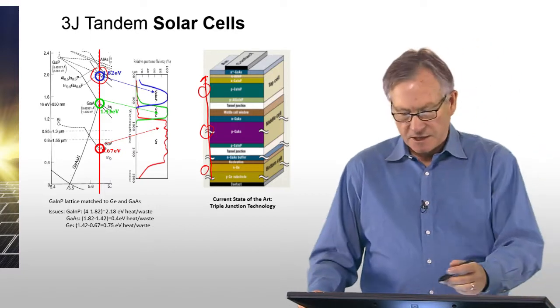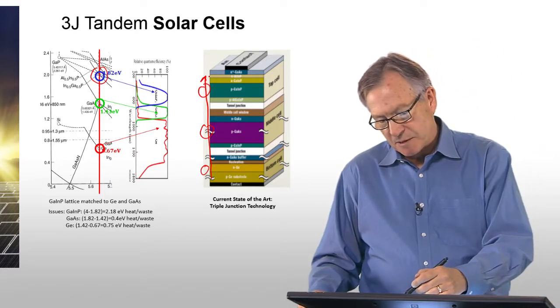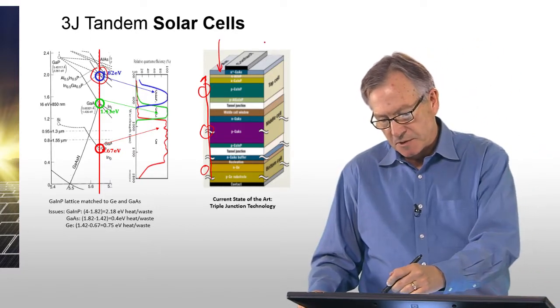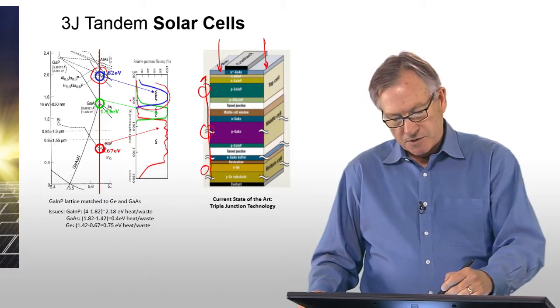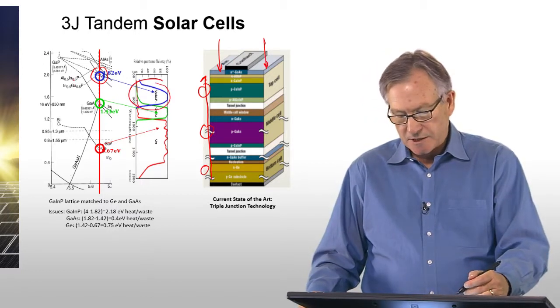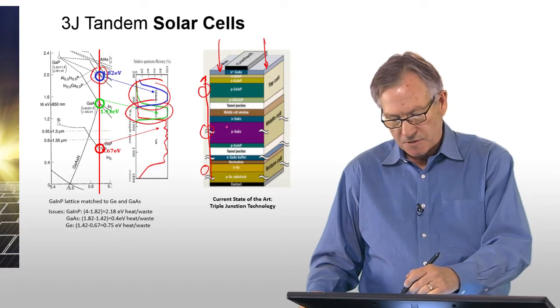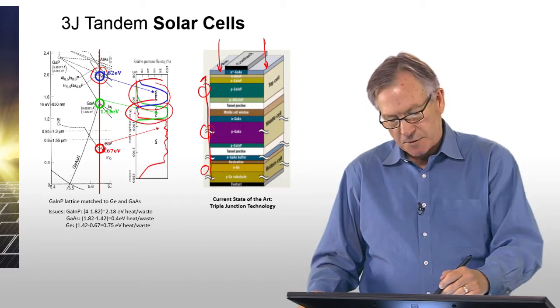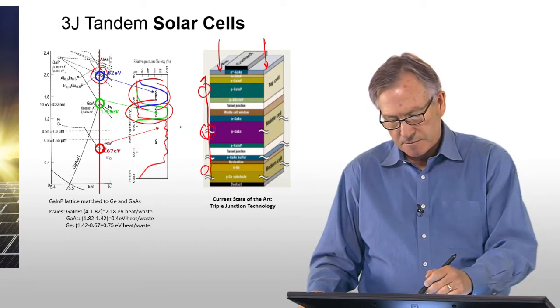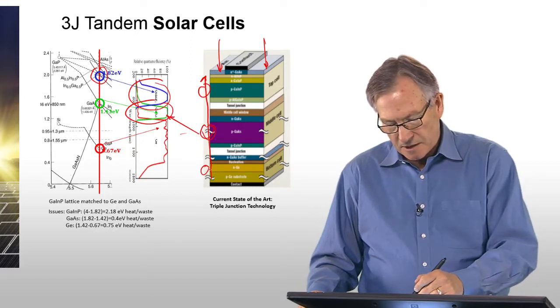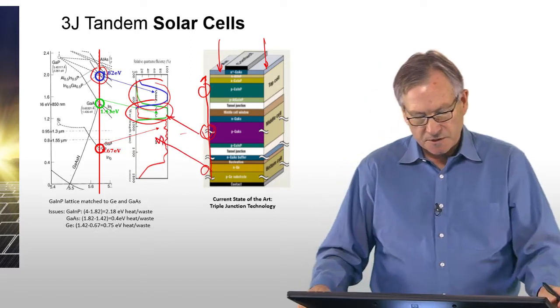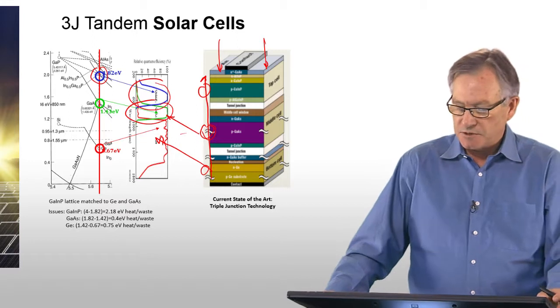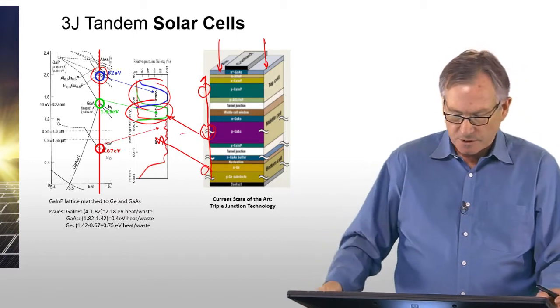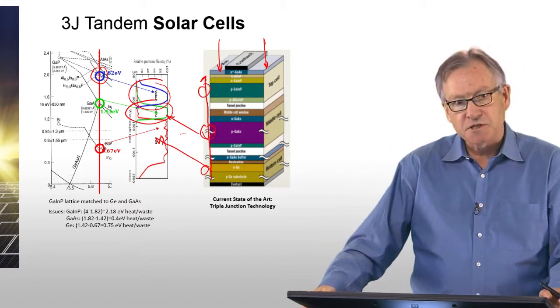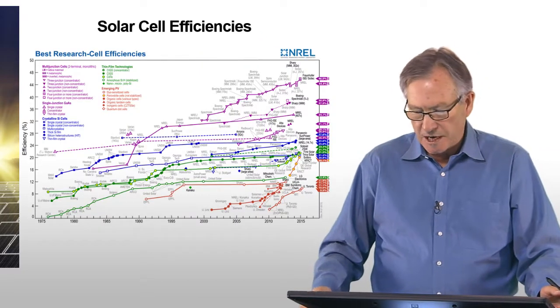But as I discussed, the wide band gap cell is on the top. Light is coming in from the top. Part of it's harvested in the gallium indium phosphide layer. The next part harvests the photons that are left in the gallium arsenide layer. And then finally, the rest of the photons are harvested in the germanium layer. And so in this way, with this three-junction solar cell, you can achieve efficiencies that are substantially higher than the Shockley-Queisser limit.